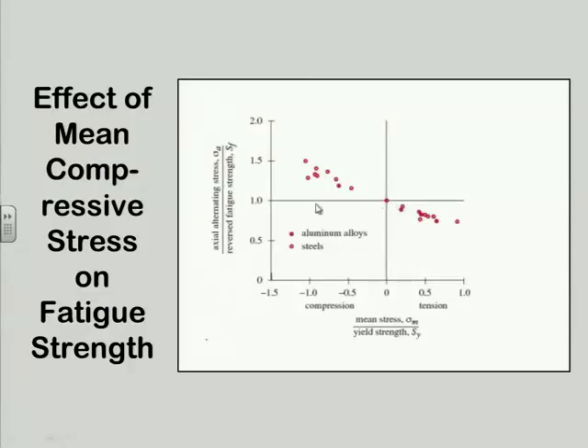But this now goes into the compression regime. So here we have tension to the right, compression to the left, shown as negative values. And this is also the same mean stress versus alternating stress, alternating on the vertical axis, mean on the horizontal. But the data are taken back into the compressive regime, and notice that the stuff is stronger under compression type stress, and it breaks at values, it has more strength, put it that way, than the endurance strength in tension, which is right here on this axis. This is the alternating axis right here.